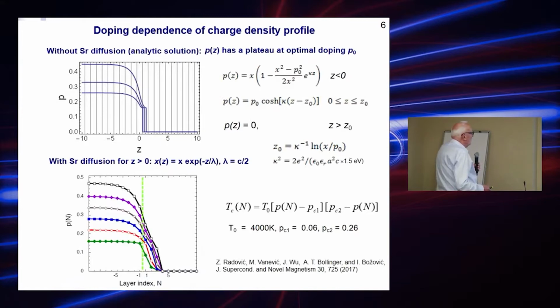Okay, when we solve with this assumption of dependence of chemical potential on P, we obtain, as expected, something like this, and we can explain in this way that first, second, or third, depending on X, a layer is doped, optimally doped to the level of 0.16, and this gives the maximum critical temperature. It's easy to solve analytically, but to take into account the strontium diffusion, we solved numerically, including the strontium diffusion measured experimentally, and we obtained practically the same results.